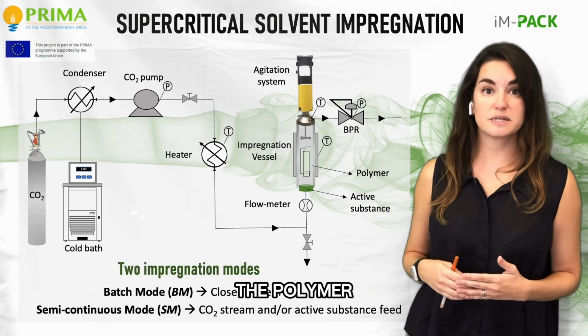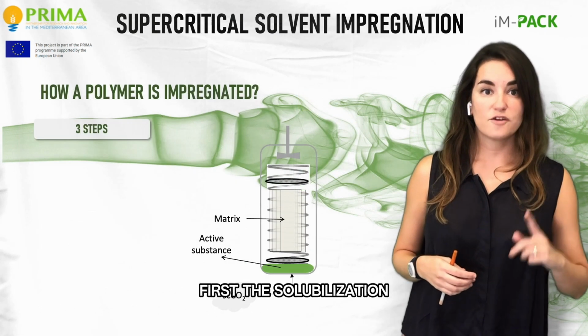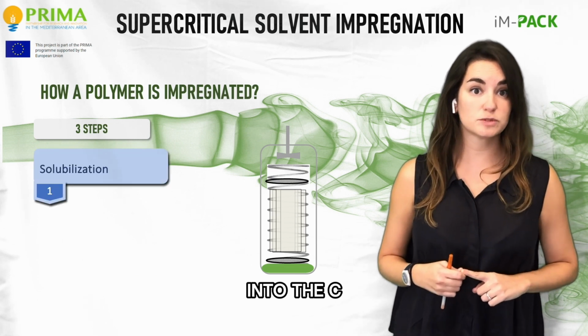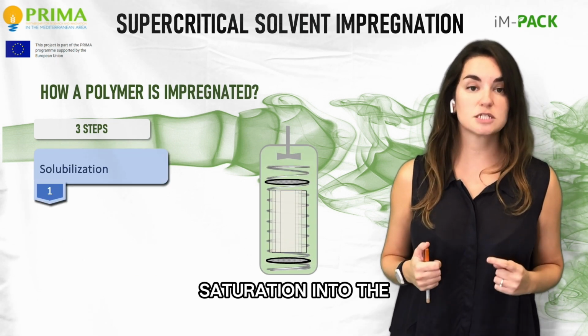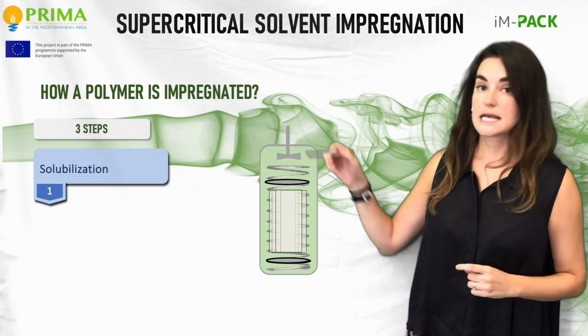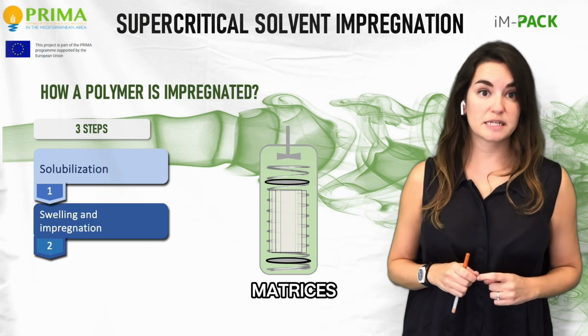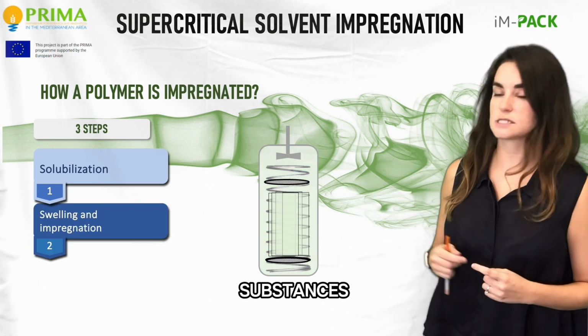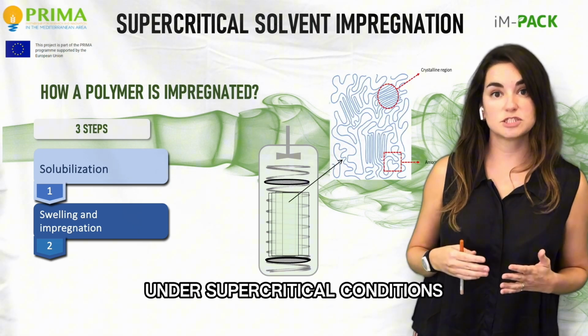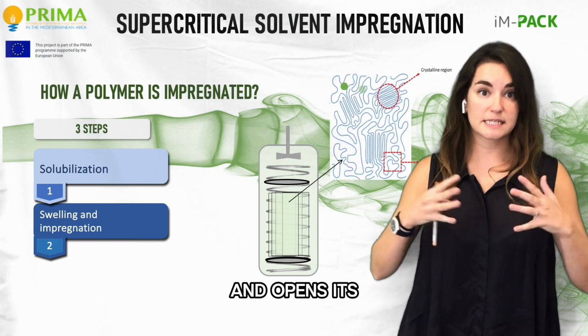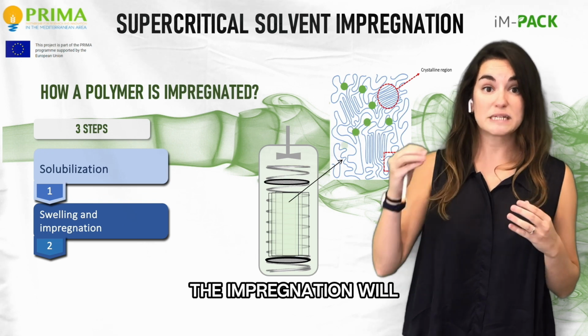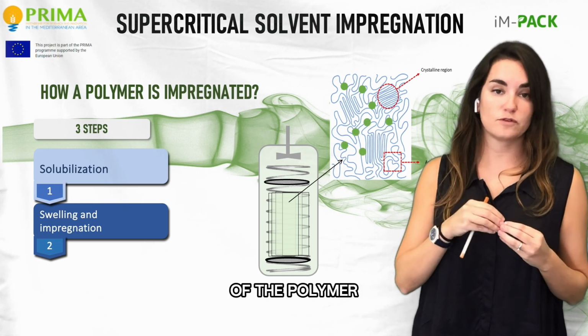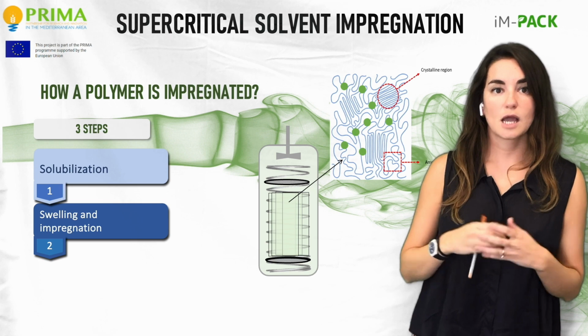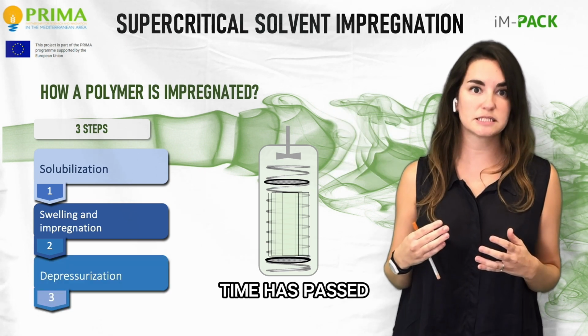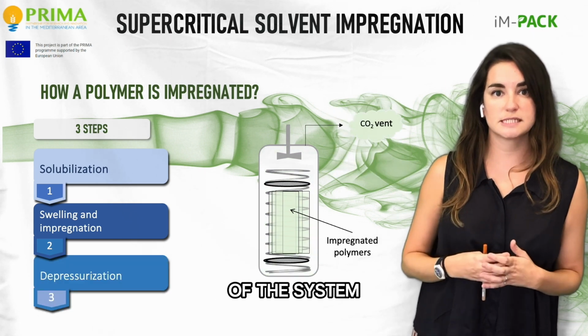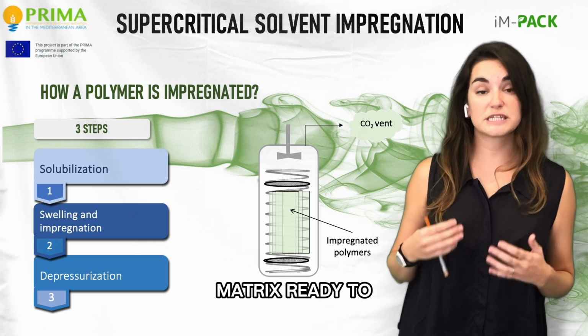The impregnation of polymer is carried out in three steps. First, the solubilization of the compound into the CO2 and its saturation into the vessel. Second, the swelling of the polymer matrix and the impregnation of the active substance. Under supercritical conditions, the polymer swells and opens its pores. The impregnation will take place mainly in the amorphous region of the polymer. Once the impregnation time has passed, the depressurization of the system is carried out, providing then a matrix ready to use.